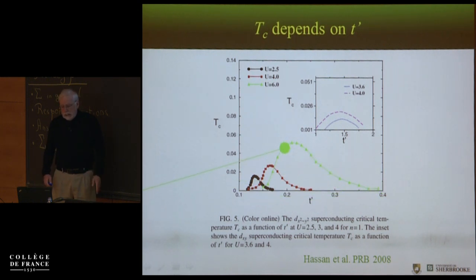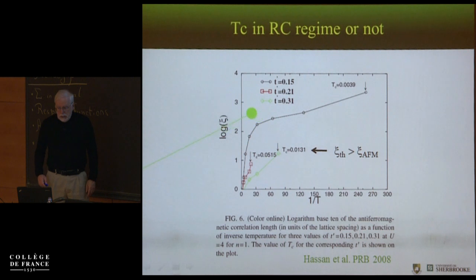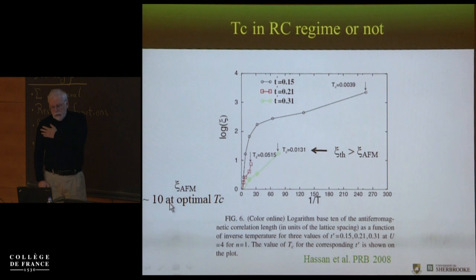And then you may ask, like Catherine did, where is the antiferromagnetic quantum critical point? We have not located it precisely here, but I just know that there's a region here where we are not in the renormalized classical regime. In other words, the antiferromagnetic correlation length is less than the thermal de Broglie wavelength. So this is shown by this plot. I plot the log of Xi as a function of 1 over temperature. And for this T prime equals 0.31, so that's far to the right, the thermal wavelength is larger than the antiferromagnetic wavelength. And what we know also is that the antiferromagnetic correlation length at optimal doping is about 10.